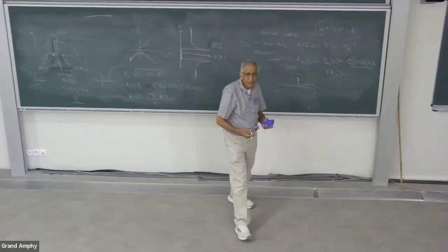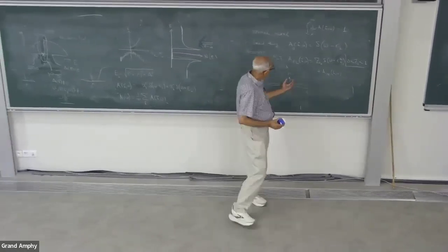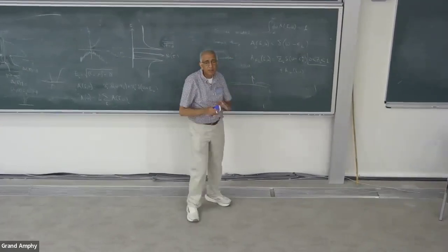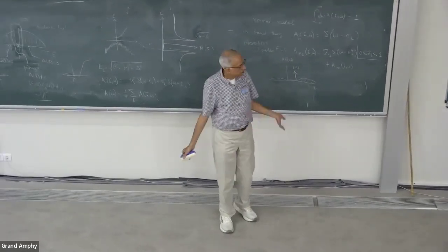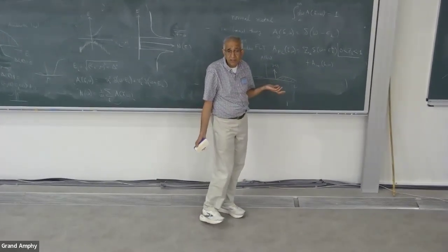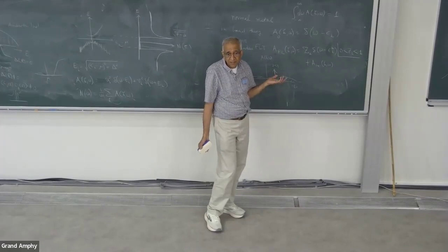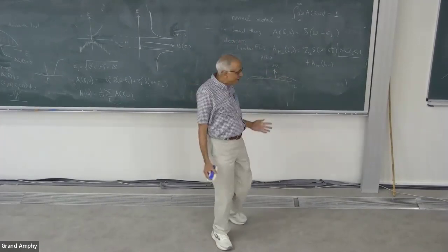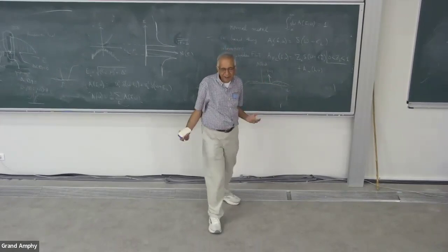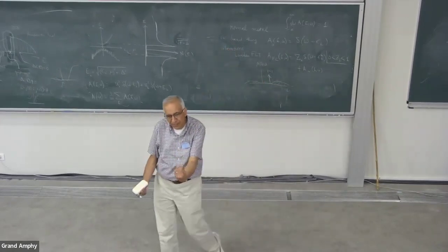So what I'm saying is, if you come close enough to the Fermi surface in Fermi liquid theory, you must have a pole. Now, if the residue at that pole is very small, maybe it's hard to see in an experiment, and everything looks incoherent. If 99% of it is in the incoherent part, then it will not look like a pole unless you can do really sharp